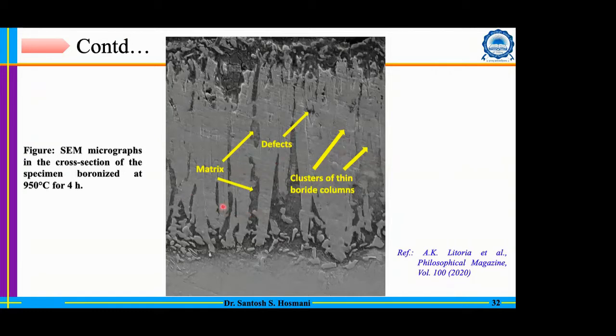Now here you can see an enlarged view. The bigger boride columns are formed by clustering of thin boride columns during the growth process. You can still have some trapped matrix region. And you also have the formation of defects, especially near the surface region, and these defects are mostly porosities.